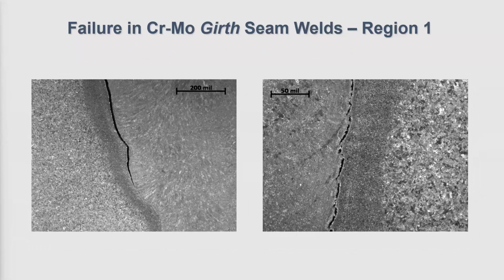This is actually a girth seam weld showing failure along the same location, in the weld metal immediately adjacent to the fusion boundary. In this case, the weld was given a subcritical heat treatment, so there is a heat affected zone, and yet despite the presence of the type 4 region, the damage has actually occurred in the weld metal because in this particular set of circumstances, this was the more vulnerable area, and so that's where the damage actually formed.